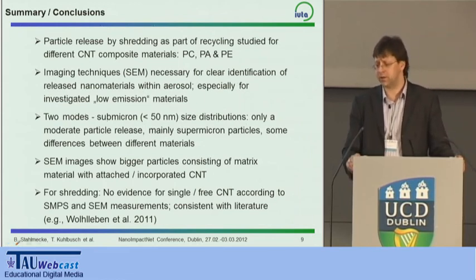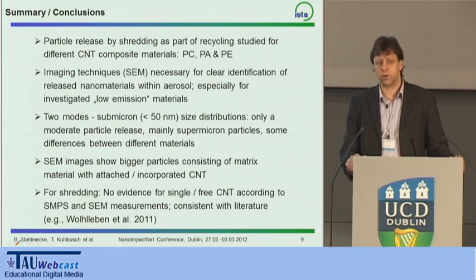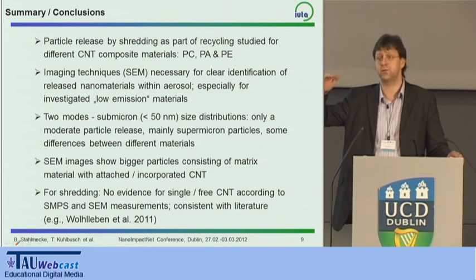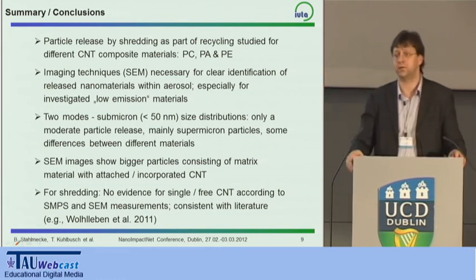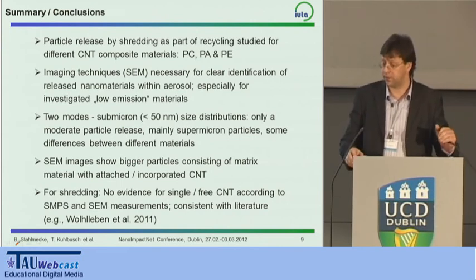In summary, for this study at least, particle release by shredding was studied as part of the end-of-life cycle, which may take place with the composite material polycarbonate, polyamide, and polyethylene. To resume, similar to what was said before, it was not easy to detect any fibers online, in situ, in air, so we had to have a look using SEM pictures. We always detected 2 modes, one in the supermicron and one in the submicrometer size range. And in the bigger particles, we could clearly identify the fibers being enclosed and still attached, either on top of it, which we could see sometimes, but in most cases really embedded still with one end in the material itself.